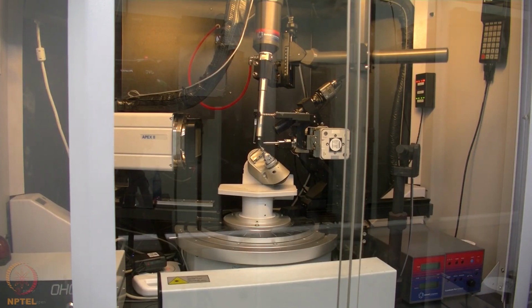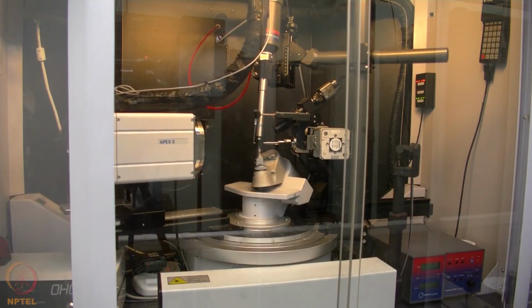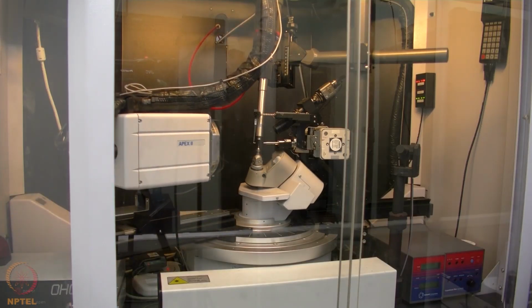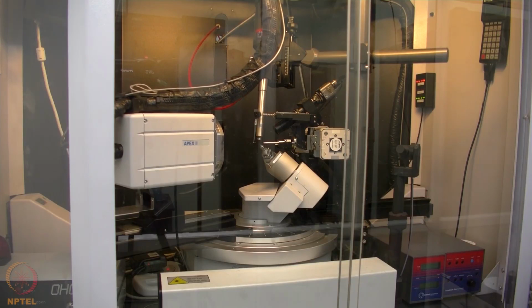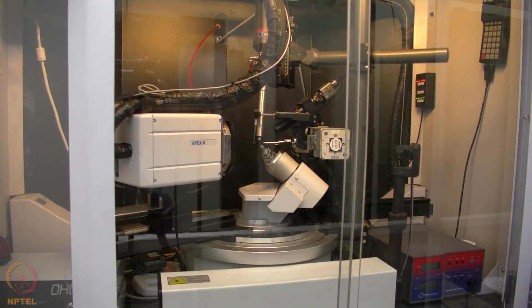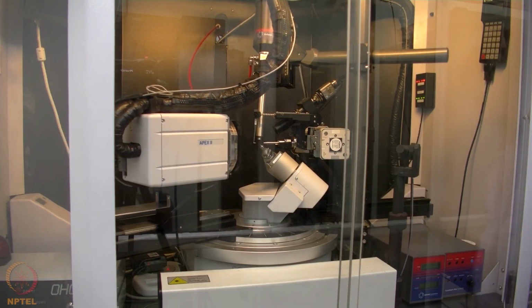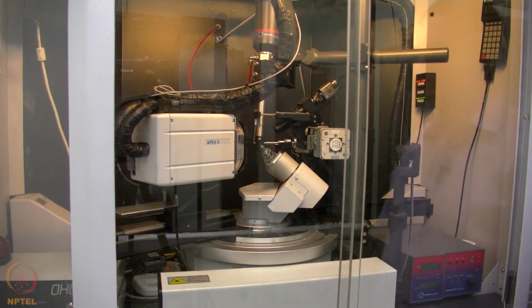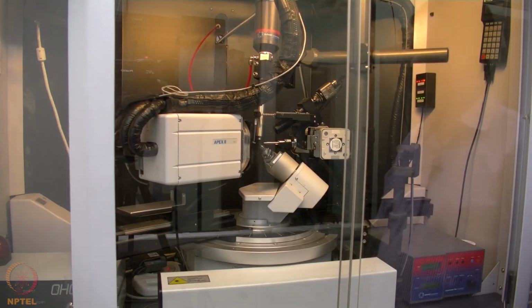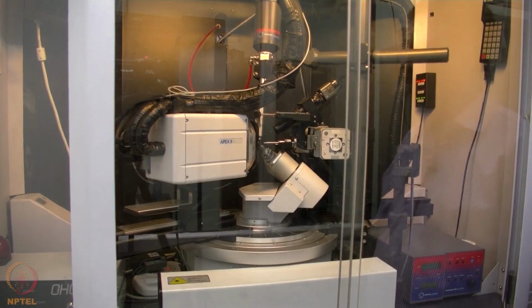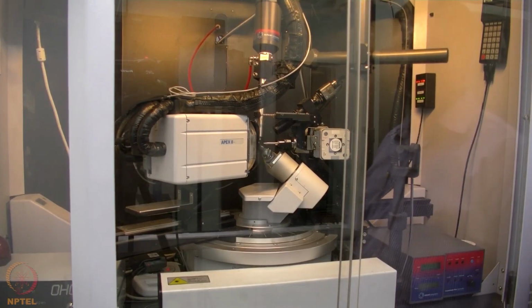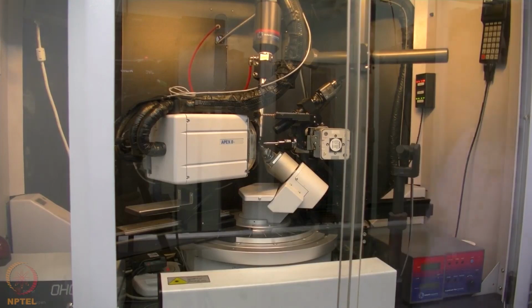You will see on the screen how the axes move. You can see that 2 theta has come to an angle of about 30 degrees and omega has gone to about 30 degrees, kappa is in a new position, and now the detector is moving closer and it is coming to a distance of 6 centimeter. So now the sample to detector distance is 6 centimeter.